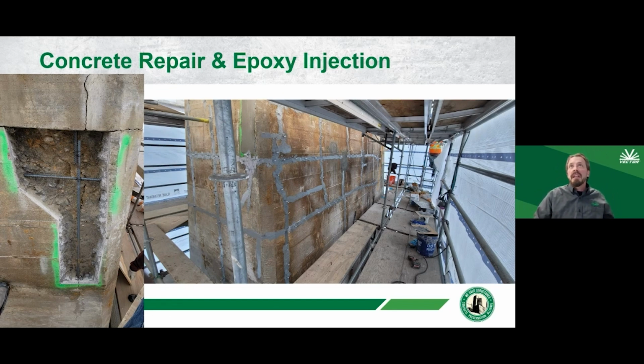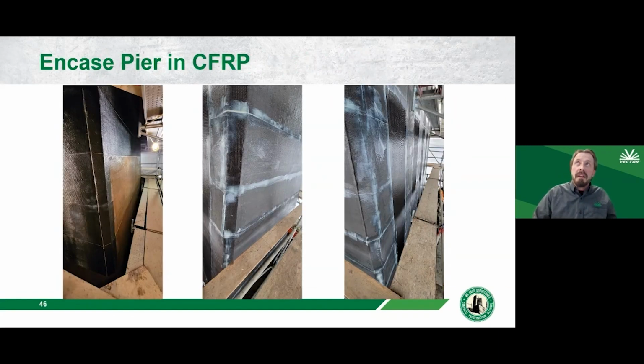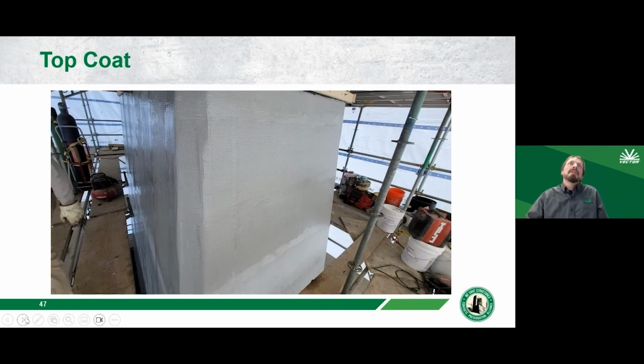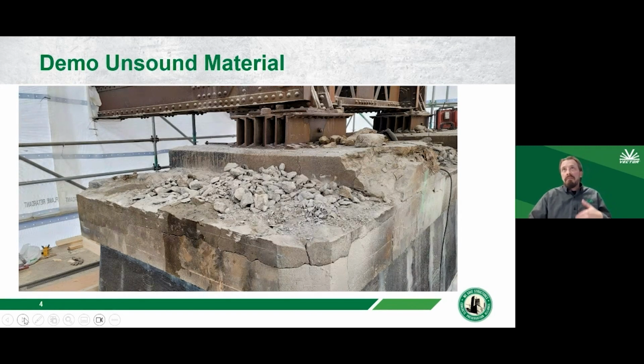Once all of that was done and completed, perform the surface preparation, and then wrap this pier in carbon fiber. So rather than building a big encasement or something like that, in this case, perform the chip and patch repairs, fix the cracks with epoxy injection, then wrap and confine it. And then, as you can see, there's some vertical placement of FRP. So that designer, that's what they had detailed for this project. Once it was complete, top coated it with a UV stable coating.